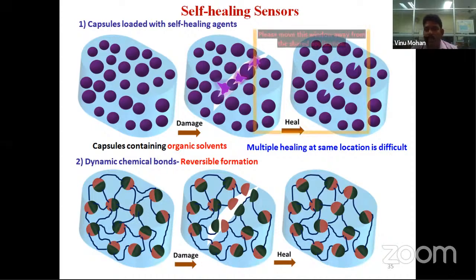So once we damage some of the capsules, what will happen? Then there are no more capsules available with the healing agents. So for that purpose, we can use another approach. While preparing the electrodes, we can have dynamic chemical bonds. These chemical bonds can form a reversible bond. And whenever some damage occurs, instantaneously, the reversible bond formation happens, and it leads to the self-healing process.